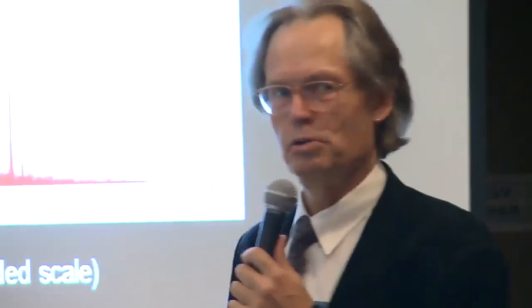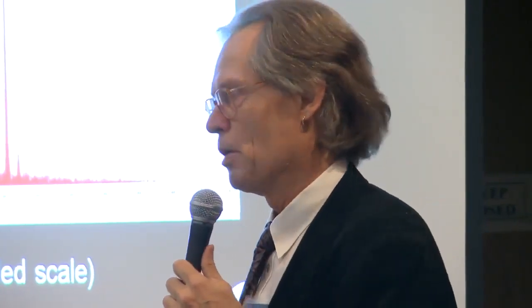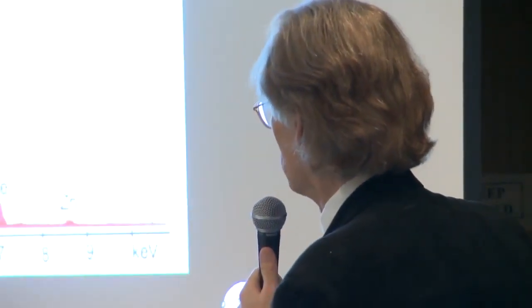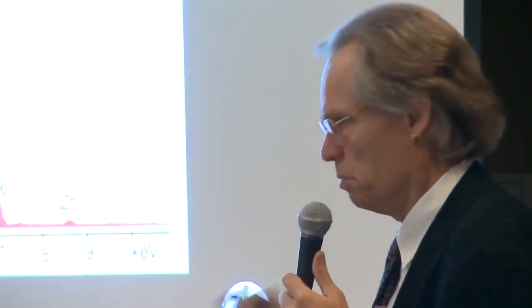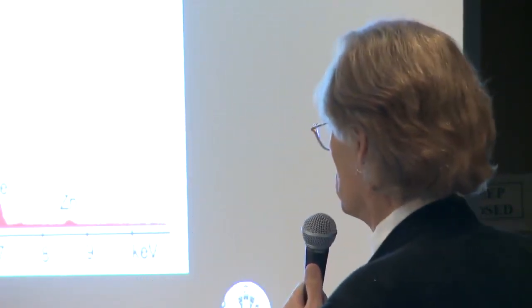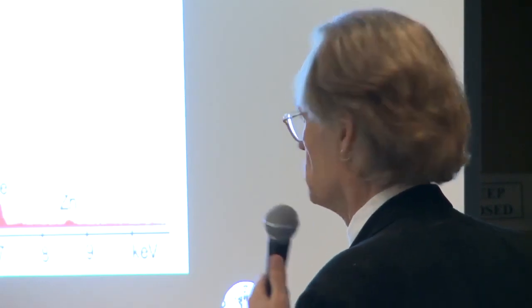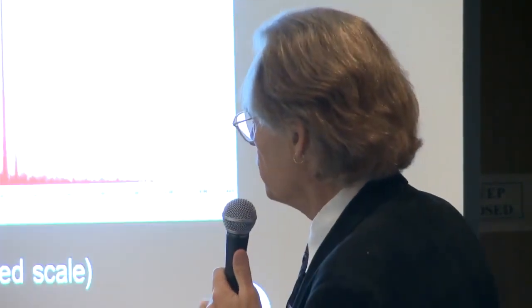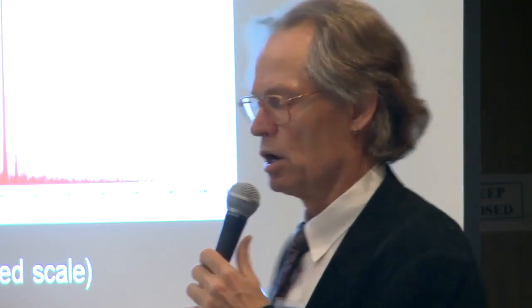Now then, I'm just telling the experience that we have had with the debunkers. They fell down on one of the pictures in the paper here, which shows the chip which was used for the swelling experiment with methyl ethyl ketone. They say, ha! You see here you have chromium and here you have zinc. That is proof that it's a primer paint. The point here is that in the previous picture, these EDSs have been taken on chips which have been broken, so you have a clean surface, which is the way to do it.